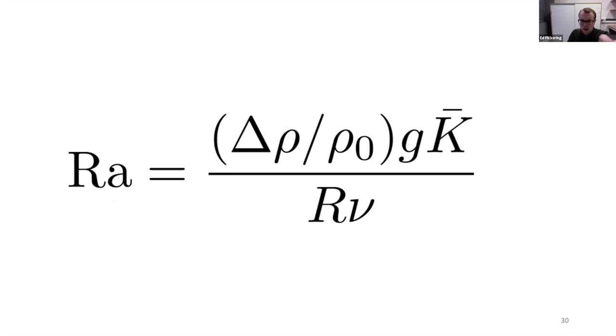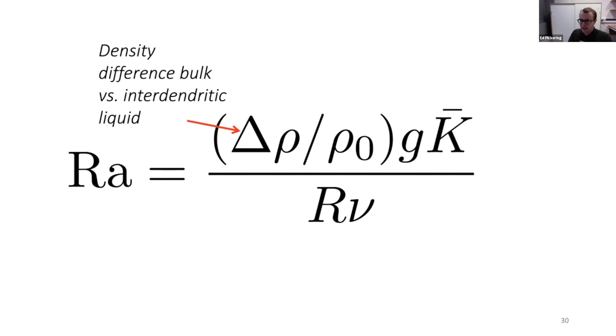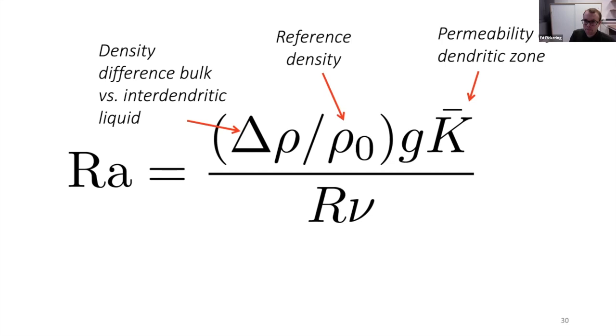Firstly, as you might expect, the density difference between the bulk liquid and the interdendritic liquid is really important. That goes on top of this equation. The higher that is, the more fluid flow you're going to get. Okay, there's a reference density in there. There's the permeability of the dendritic mushy zone. Okay, so if you have a higher permeability, you're more likely to get these channels forming.